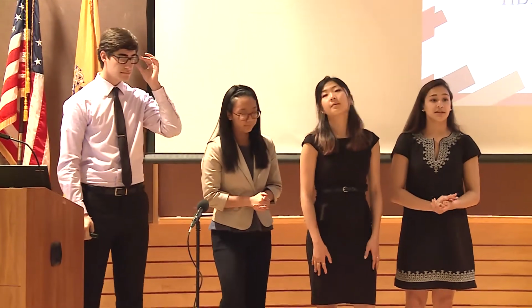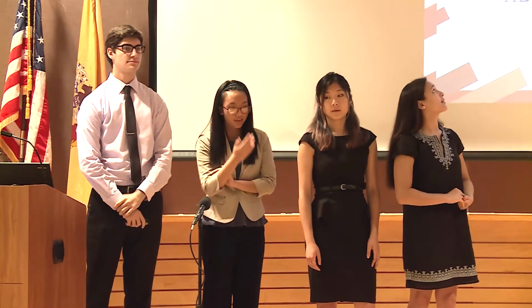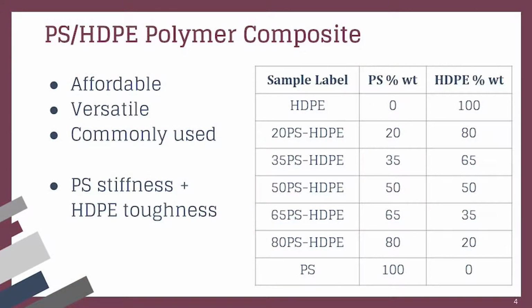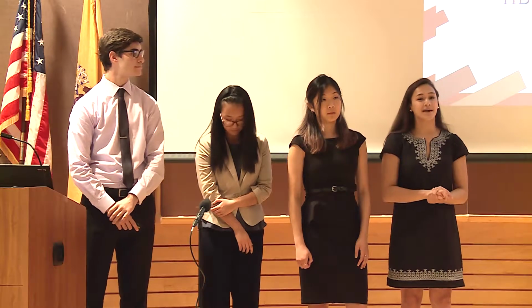As Ali mentioned, the two composites we'll be making are combining polystyrene and high-density polyethylene. These plastics are being used because they're very cheap, they're versatile and commonly used. We will be increasing the weight percentage of polystyrene, from 0% to 20, 35, 50, 65, 80 to 100% polystyrene. And we hope to increase the stiffness of polystyrene and maximize on the toughness of high-density polyethylene.